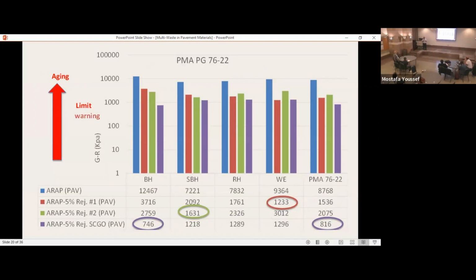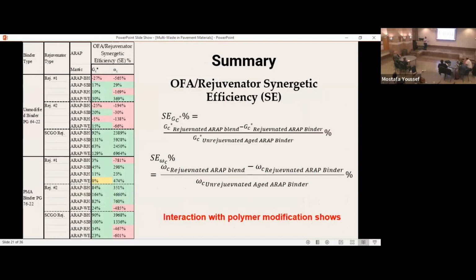But the picture changes significantly as you go to the polymer modification. Again, the dominant component in the polymer modified binder is the polymer, especially if it's cross-linked like the one we're using. So the incorporation of the particulates sometimes even impedes the effect of the polymer. The improvements we see are scattered all over the place. We don't see significant worsening in the fatigue cracking susceptibility. The performance stays the same for the most part, for all the different combinations.